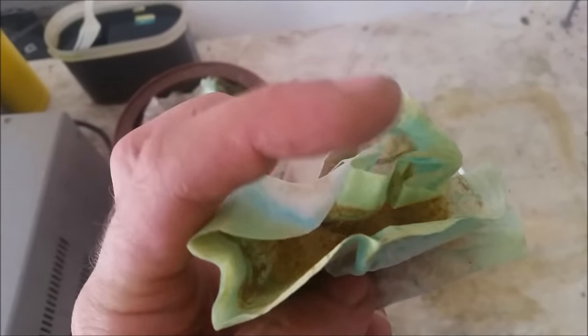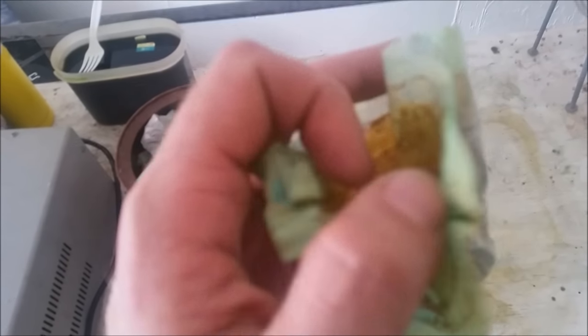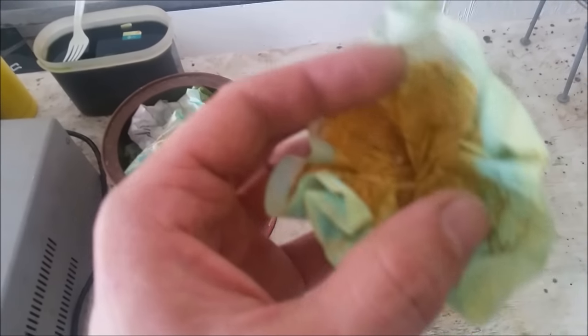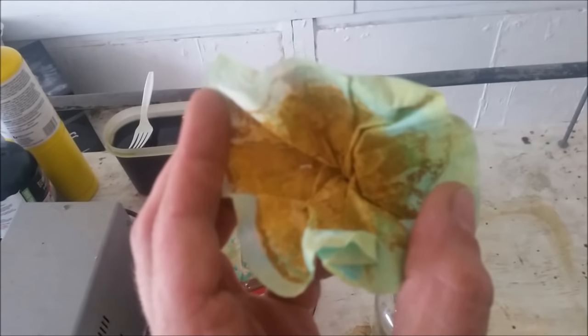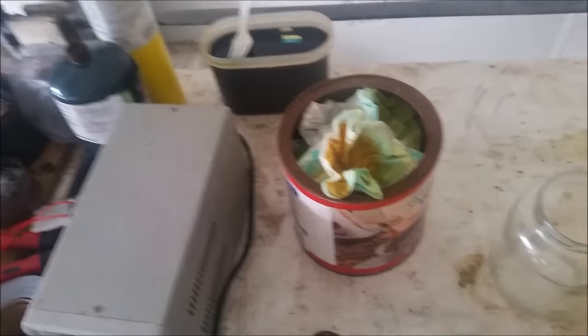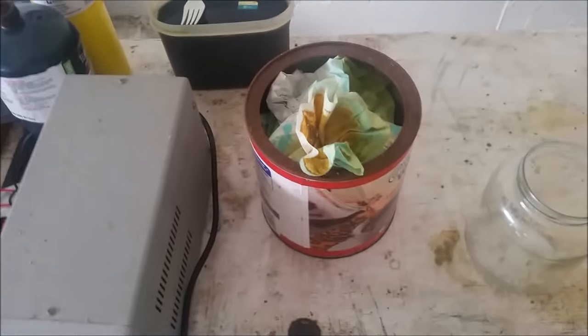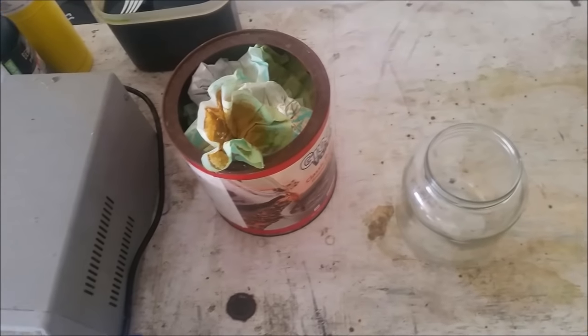It will be very easy to remove. If you look inside these filters, there's a powder in there — it's metal. Anybody who has worked a lot with electroplating copper knows that that is not copper sitting in there. It is probably a whole mixture of things such as lead, tin, gold, silver — just whatever else is left in copper after it's refined at the factory and turned into wire.